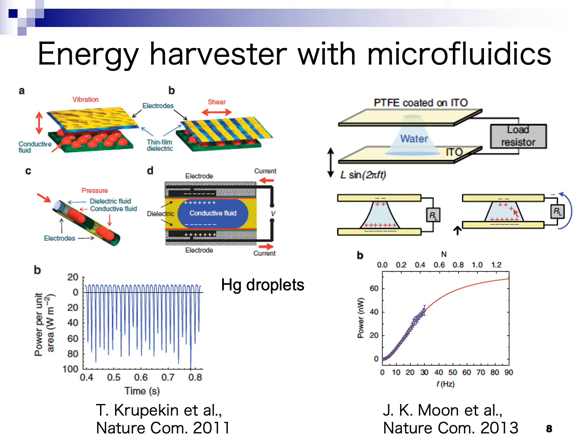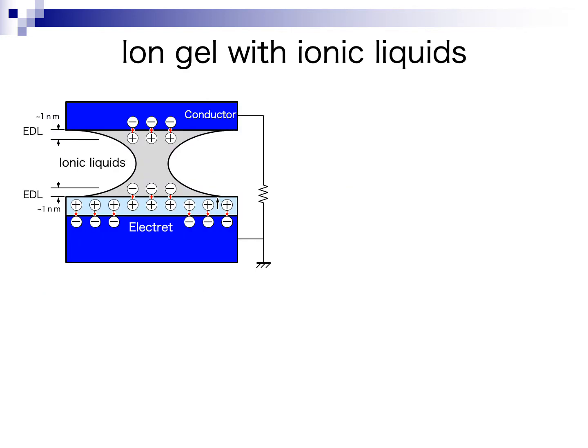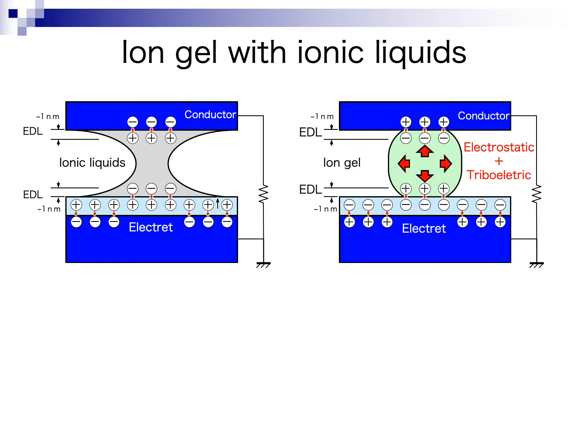So we try to use an ionic liquid as an electrolyte. In the beginning, we directly put the ionic liquid on top of the silicon electret. But due to the electrostatic force, ions immediately attach to the surface of the electret, and we cannot change the surface area efficiently. Then we try to use ion gel instead of the ionic liquid. Indeed, we can change the surface area which attaches to the surface. But still, we need to use the electret to sustain the electric double layer, or we need to use another power source to sustain this electric double layer.